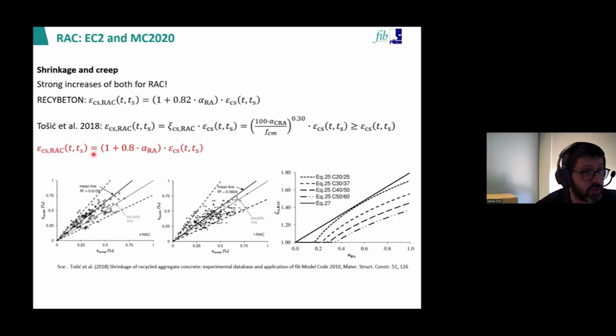There are increases in shrinkage and creep. Here we had also carried out already meta-analysis, both within the Vesibeton project and our own research in Belgrade and Barcelona. So we compared, in the right image, the two expressions that the two research showed, and they coincided quite a bit. And so we proposed an increase where you calculate shrinkage as if it were natural aggregate concrete, and then you multiply it with 1 plus 0.8 alpha. That is a significant increase, because if you limit to 0.4, then you are increasing shrinkage by 32%.